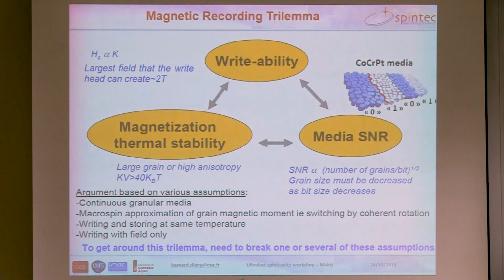The media which are being used in a hard disk drive are actually granular media, and for perpendicular recording, these are cobalt, chromium, platinum media consisting of grains separated by grain boundaries. And when we want to write a 0 or 1, basically, we set a bunch of grains in the up or down direction. And the boundary between bits, between 0 and 1 or 1 and 0, is not a straight line, actually. It follows the boundary of the grains.